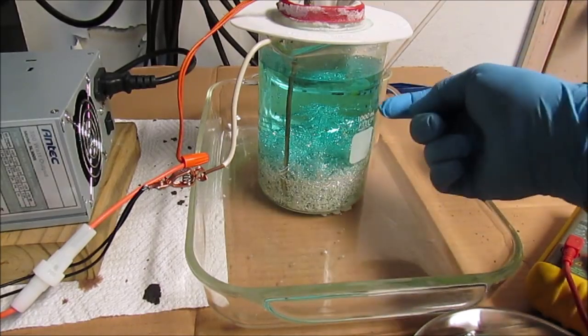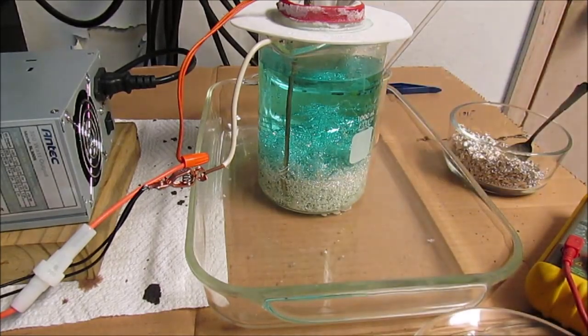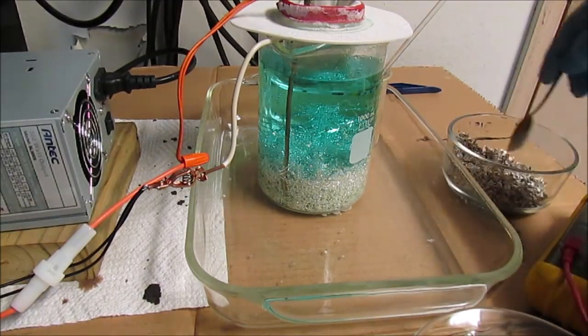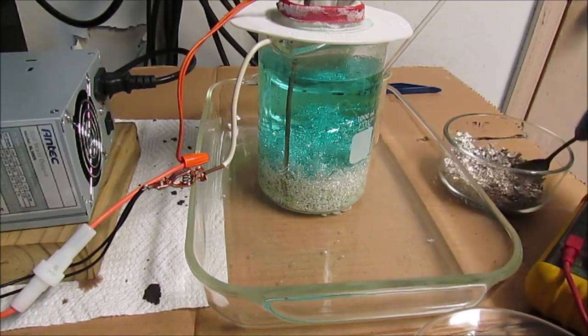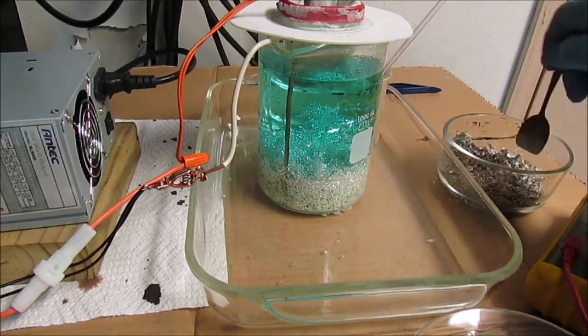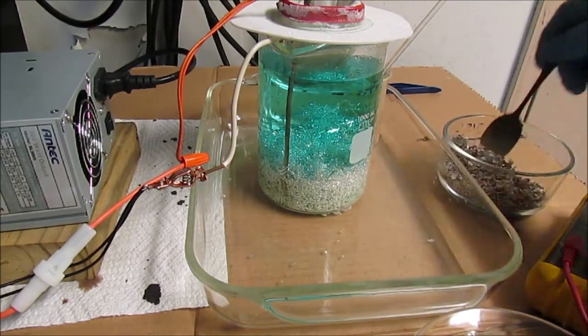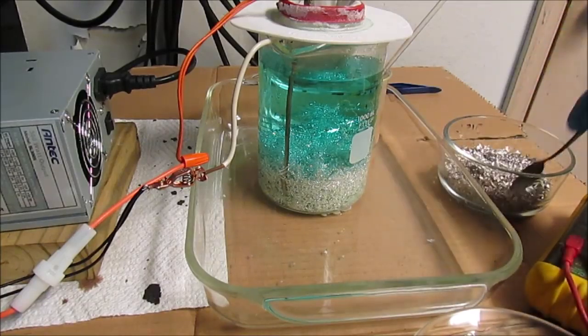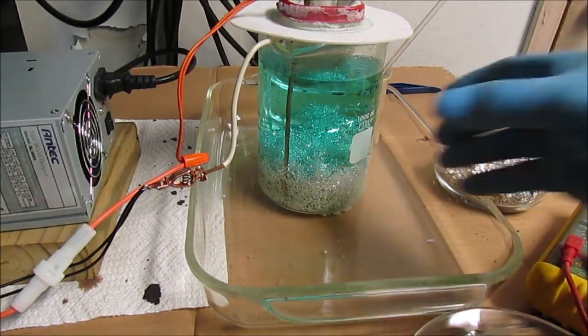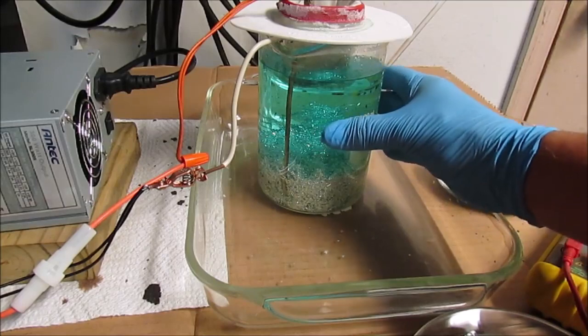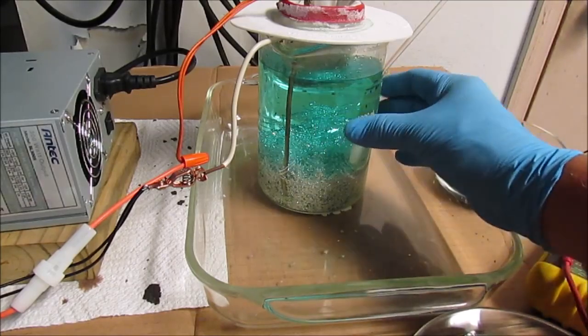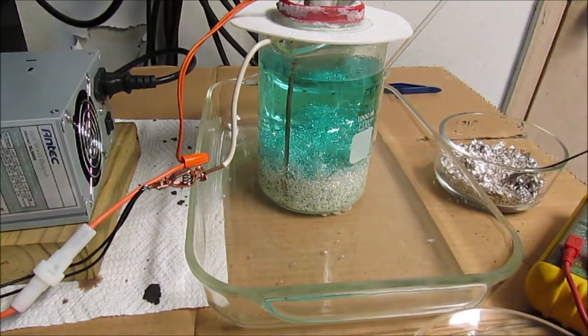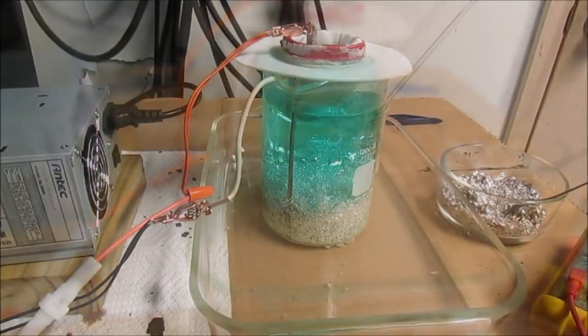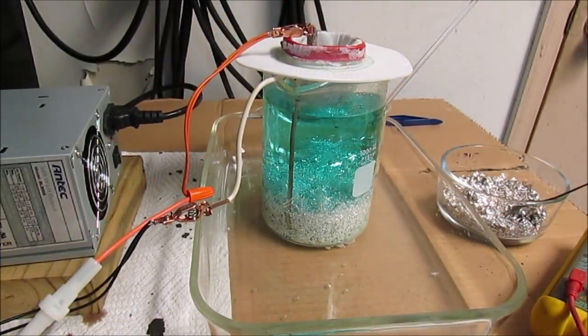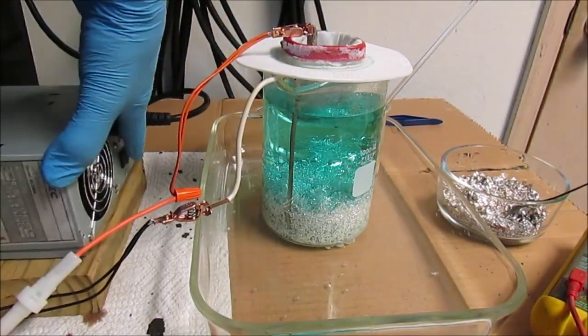Notice that the color of the electrolyte is turning blue. That is from the copper that's in the impure silver shot that we're putting through the anode filter up here. The copper dissolves and goes into solution into the electrolyte. It's not a problem, and the silver cell will tolerate up to 60 grams per liter before the copper starts plating out with the silver. All right, we're going to go ahead and turn the power supply off here.